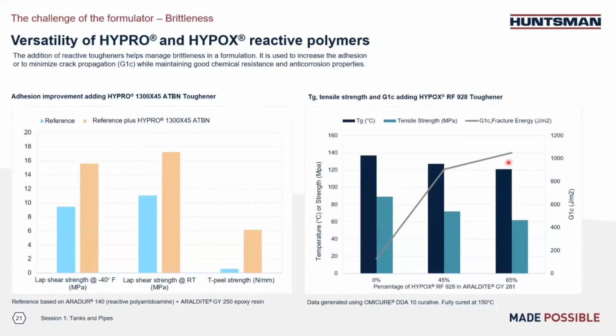If we further add toughener into the system, let's say we add 65%, you can see the G1C is only increased to 1,000, just another 10% improvement. But we see the TG dropping from 137 to 120, so the TG drop is getting bigger. So in this particular system, we would recommend using 45 as the loading amount. You might think 45 is too much, but actually, for this HYPOX RF 928, we only have about 20% elastomer content. So in the total final formulation, it's still only about 9%, and we're still within that 5 to 15% range we mentioned earlier.